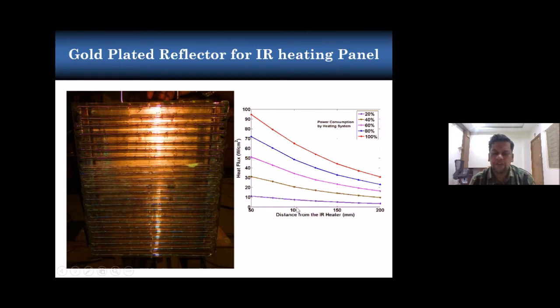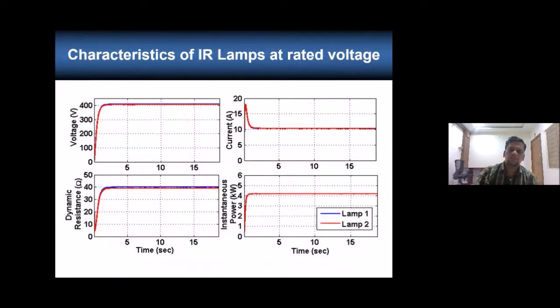Then if I move 50 mm away from the heater, my flux will come down to 70. So almost a 25 watt per centimeter square flux reduction will be there. If you want more flux, we have to keep our object very near to the heater. Then the participating media between the heater and object also matters while receiving the radiation from the heater.